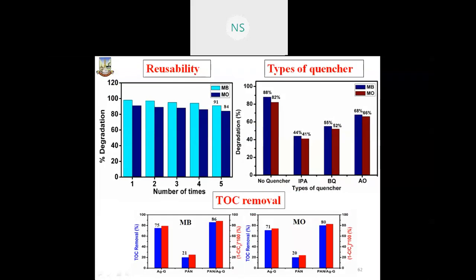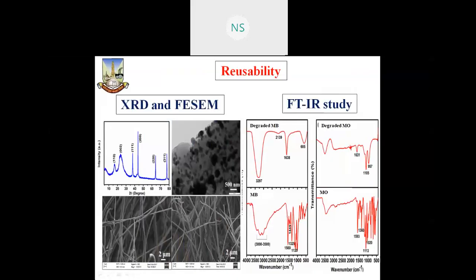So this is the reusability of this material. We can use this material up to the fifth cycle, and up to the fifth cycle it shows 91 to 84% degradation. Methylene blue shows 91% degradation, whereas methyl orange shows 84% degradation. Next. And these are the different quenchers we have added during the degradation process. This is the surface study after reusability, up to the fifth cycle. Even up to the fifth cycle, the material does not lose its catalytic activity. It does not leach out.